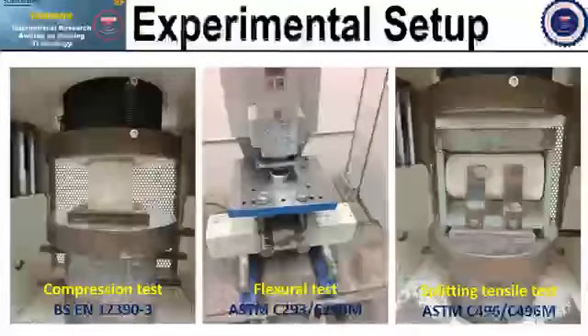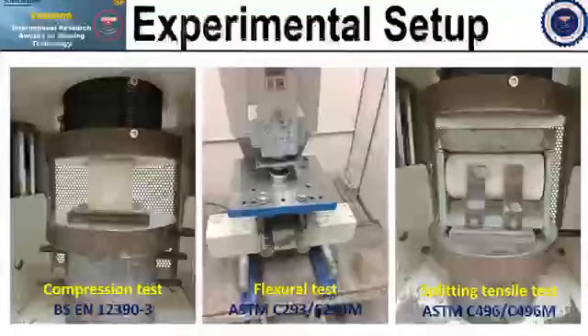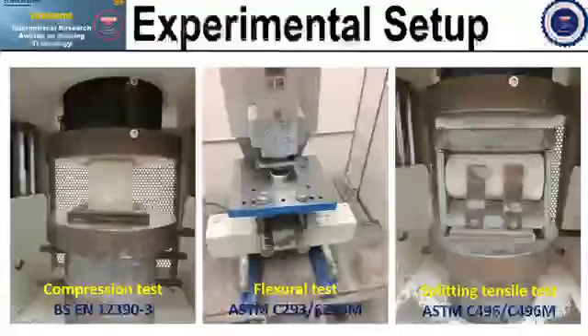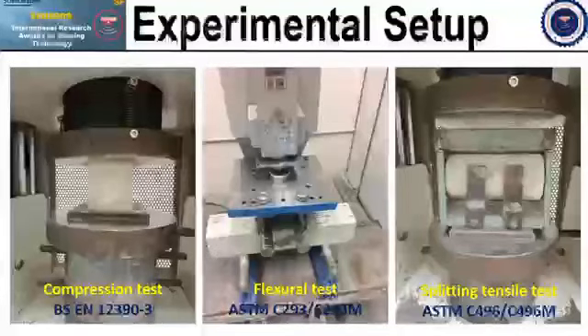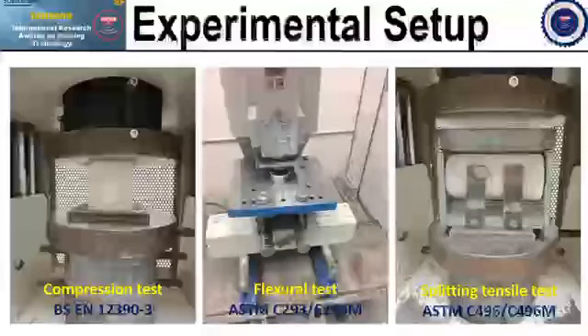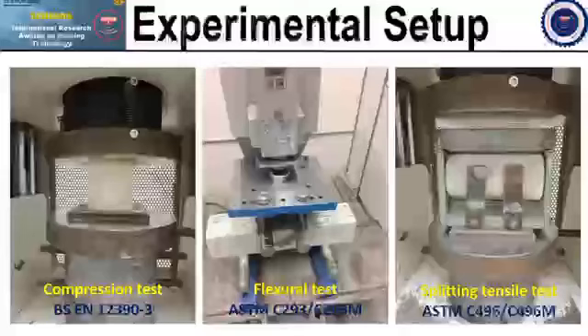Okay, tests were carried out to investigate the mechanical properties of lightweight foam concrete with the inclusion of natural fibers such as sisal, coir, and jute fibers. These tests comprise of a compression test, flexural test, and a splitting tensile strength test. Okay, the compressive strength of the lightweight foam concrete was tested on 100 times 100 times 100 mm cubes, corresponding to BS EN 12390-3. I used three specimens tested on the testing days of 7, 28, 56, and 180. And the average of three readings was verified as the compressive strength.